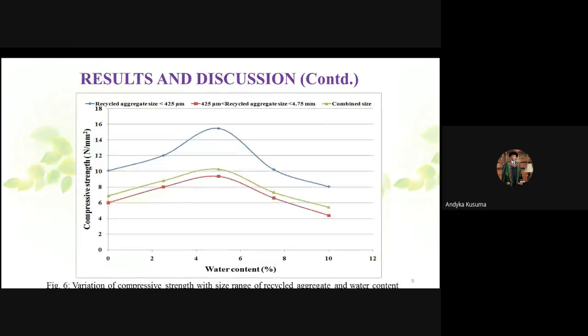This graph shows the variation of compressive strength with the particle sizes, as already discussed. The maximum compressive strength is shown by particles having size less than 425 micrometer and water content 5%, and combined particle sizes have compressive strength in between these two sizes.